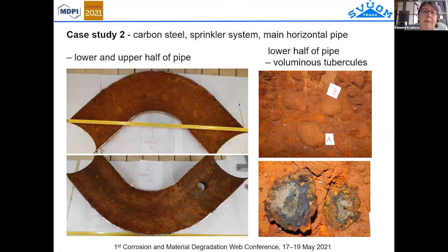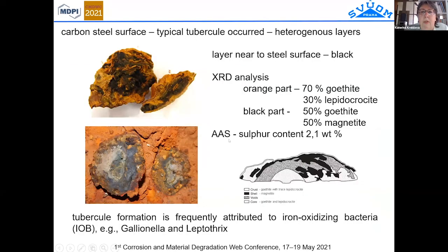The second case was also from carbon steel. This is a pipeline from a sprinkler system. It was the main horizontal pipe, and especially in the lower half of the pipe, a lot of voluminous tubercles occurred. After their cleaning, we can find that the lower part of the tubercles is a very different color. It's a non-homogeneous, heterogeneous layer which was created by goethite and lepidocrocite, and in the black part, which is near the steel surface, magnetite was also identified.